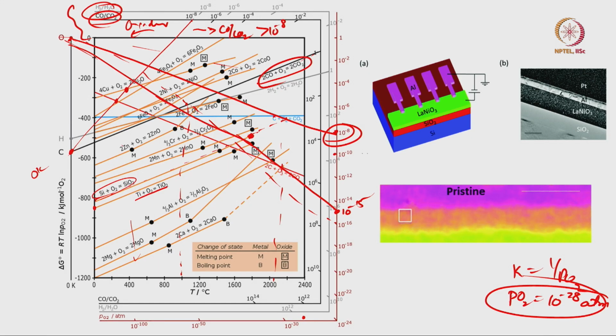So, which has a more oxidation potential, is it titanium or silicon? Just looking at this Ellingham diagram, I can say the delta G naught of silicon plus oxygen giving rise to silicon oxide at any given temperature is larger than the delta G naught of titanium at any given temperature. So, if I put both of them together, titanium will oxidize first and silicon will start oxidizing next. So, there is this window, for example. In this window titanium is getting oxidized, silicon is getting reduced.